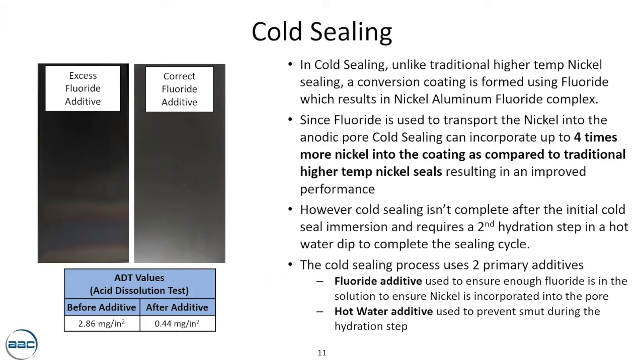So again, just like your hot nickel and mid-temp nickel, there is a seal additive to manage. The difference with the fluoride additive is it won't burn off disproportionately the same way a surfactant would. The only way your fluoride gets disproportionately consumed is when you have dropped a part in your cold seal bath, and that part sits there for weeks and slowly consumes that fluoride. But as a rule, as long as you manage that nickel chemistry and you're making regular additions, the maintenance of a cold seal bath isn't any more difficult than your normal mid-temp or high temp. In fact, it may be easier once you've set up a normal addition process.